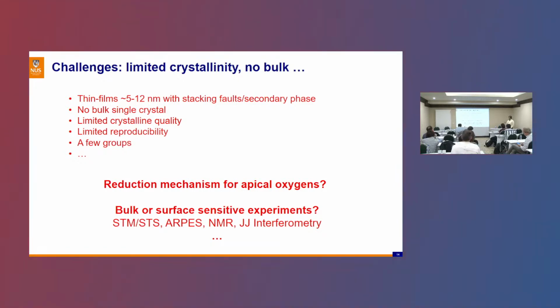So there is, of course, no bulk single crystal yet that shows superconductivity, and the rate at which you can reproduce the sample is relatively low. And again, as you can see, there are only a few groups that have been able to produce it. It looks to us that reduction is really the main issue, the removal of the apical oxygen, because we really don't have control in doing this. So of course, this also creates issues with many experiments that we are not able to do, at least conclusively at this point, like ARPES, NMR, and so on.